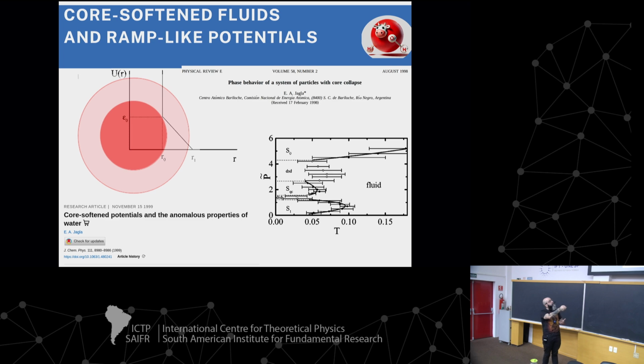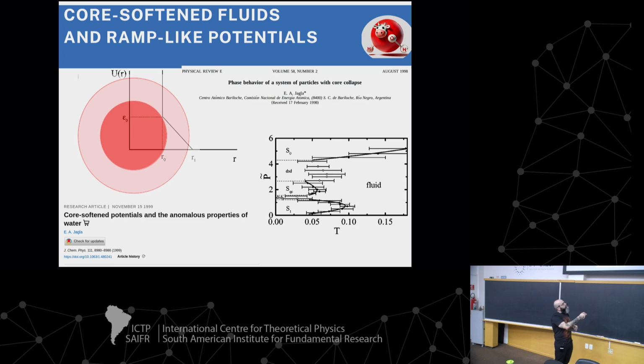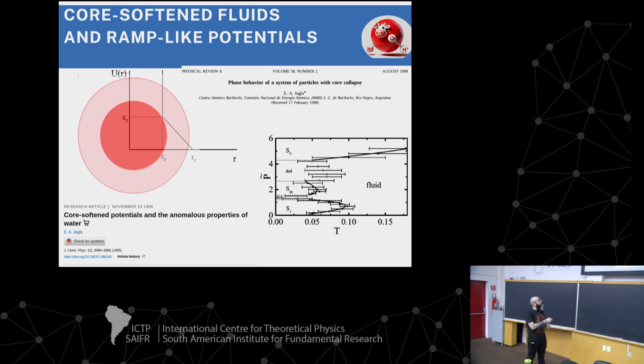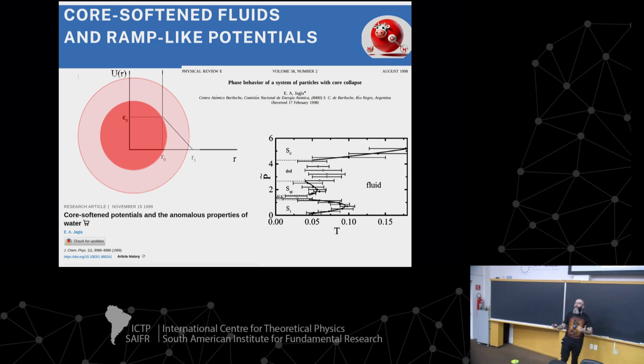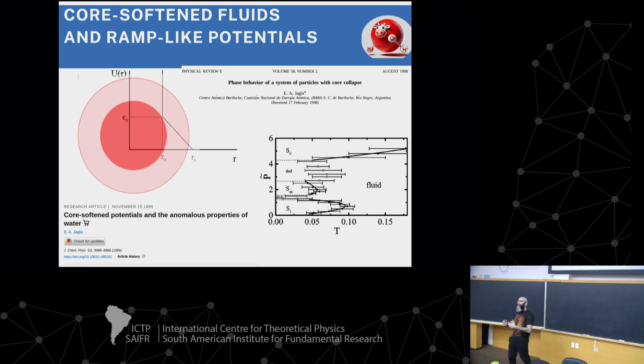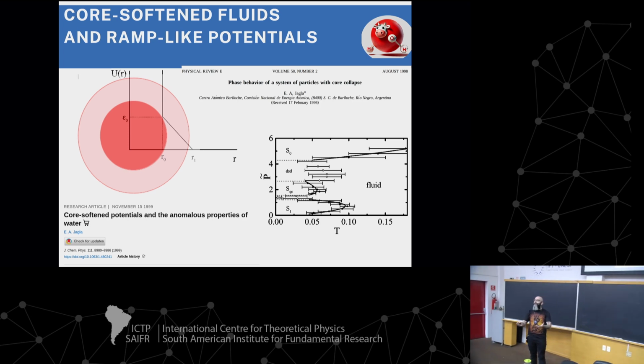This creates the idea that the core can collapse, so the particles can penetrate a little bit. He found a lot of solid phases: two disordered or amorphous solids and three ordered phases. So you have polymorphism and polyamorphism, more than one amorphous phase. And if you add a little attraction here, you can have the anomalous properties of water and the liquid-liquid critical point. As Paola said yesterday, they use this model to understand the liquid-liquid phase transition of water and to see if the transition is Ising-like or not.